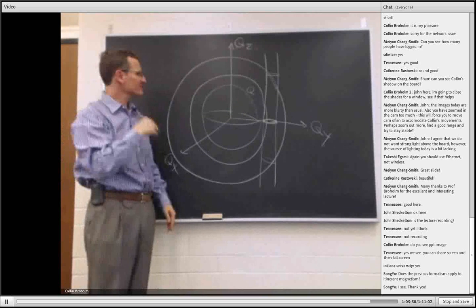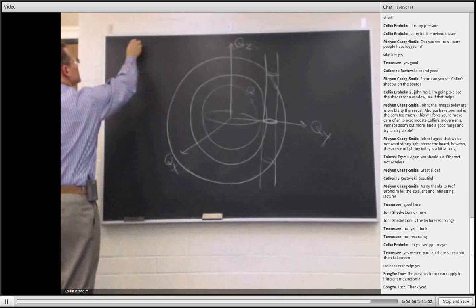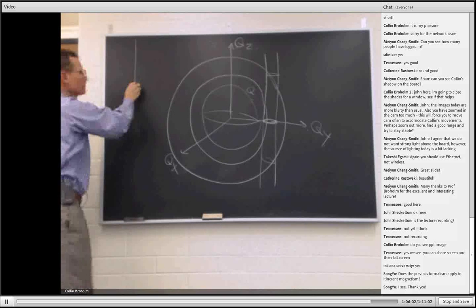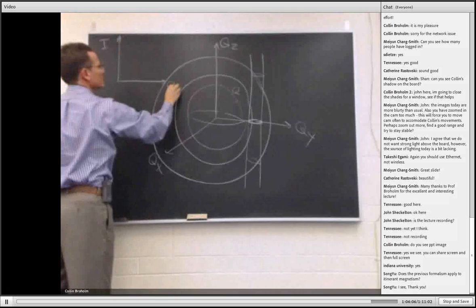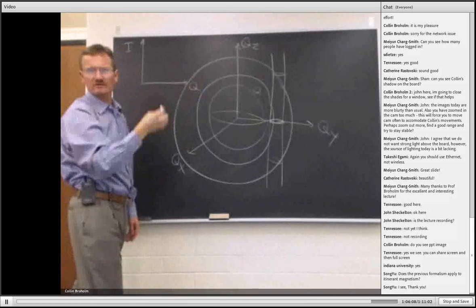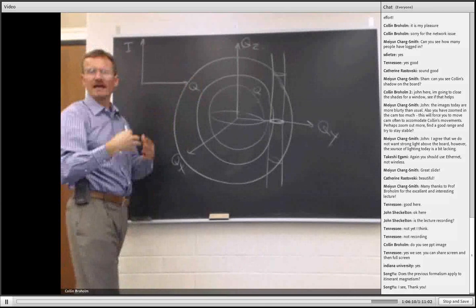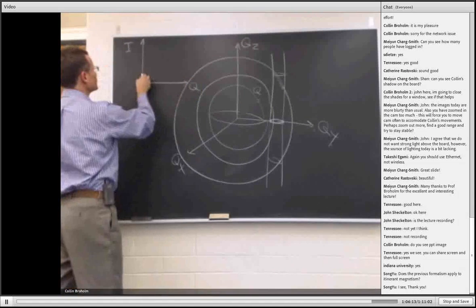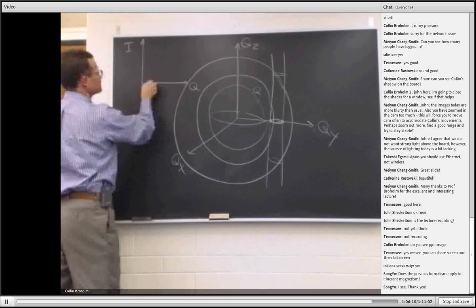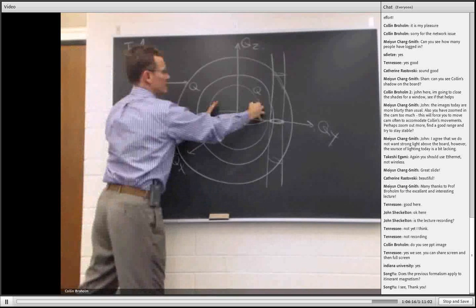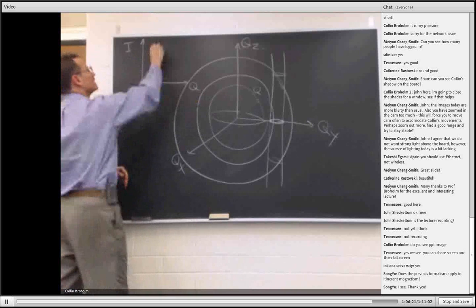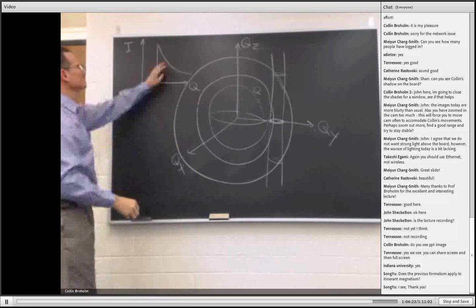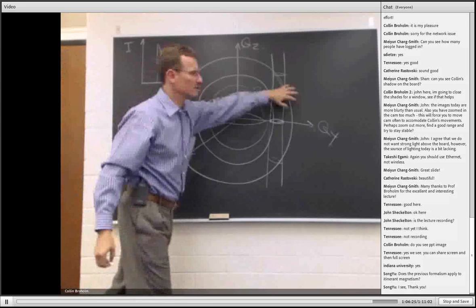So I'll just draw here the result: intensity as a function of now scalar Q, because when I'm talking about a powder sample, I only have the scalar Q. Initially there is no intensity because I'm in here. Then I hit the edge, and I get a sharp onset, and then a decrease in intensity as I walk out along that direction.